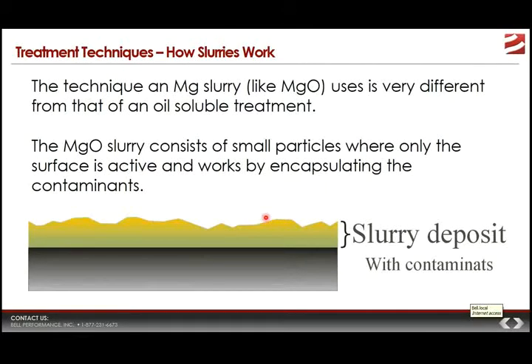First, take slurries. Slurries have been around for a while. They were actually the predominant form that was used for a long time, and for a good reason. A magnesium oxide slurry is basically a suspension of MgO, magnesium oxide particles, in some kind of carrier. They're not soluble in petroleum, which is why they have to exist in a suspension. And to their credit, it's extremely inexpensive to make. That was probably one of the reasons why what they call MagOx slurry became so well known in the industry, because it was cheap and easy to get.